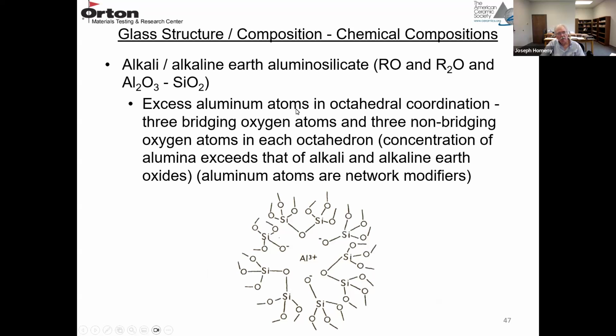So now when you have excess aluminum atoms and they're going to octahedral coordination, so there's more aluminum than the alkali and alkaline earth. So 3 bridging oxygen atoms and 3 non-bridging oxygen atoms create this octahedron. Again, concentration of alumina exceeds alkaline earth oxides. Now the aluminum ion is not a glass intermediate, it's a glass modifier. So these structures get quite complex. It's still questionable whether these structures exist or not, but this would be an Al+3 ion in an octahedral site. So here's 1, 2, 3 bridging oxygens, and then 1, 2, 3 non-bridging oxygens.